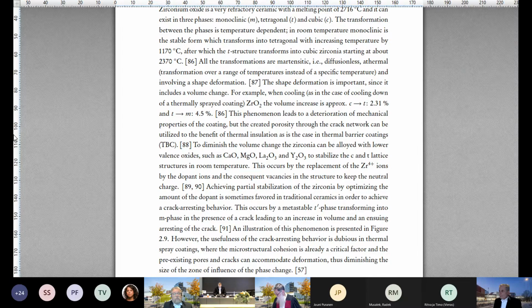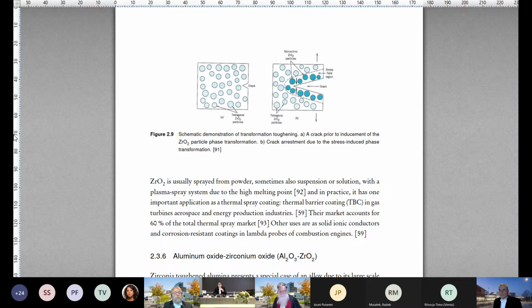So in bulk materials, this is used, like in this figure 2.9. Yeah. But in a coating, you can't find this ideal box of tetragonal zirconia particles. So if you had an intergranular crack, you might have something like that, but when it's not, then you wouldn't. Yeah, I would imagine the crack even going at the intersplat, between the splats, rather than entering the splat and causing this. Yeah. Unless the cohesion is high enough, but for now we haven't gone there. Yeah, I understand that is one of the strategies in your work, to get the splat adhesion better with nanoparticles. We come to that, I guess, later.